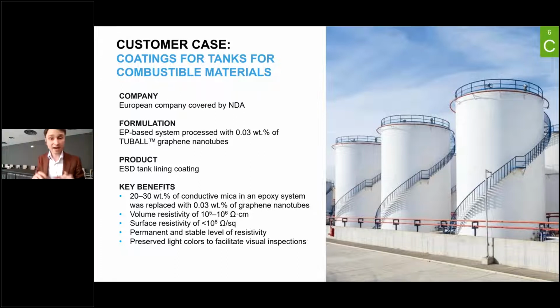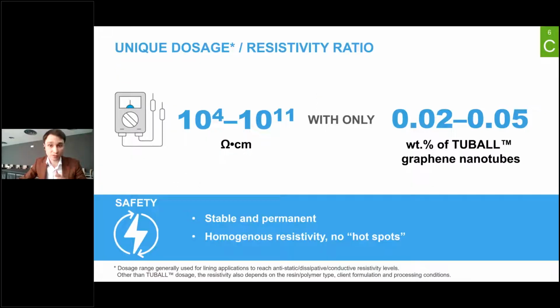And the second reason, after some time, it will be much easier to inspect defects at internal surface of tank lining coatings if it's light. Also, of course, the cleanliness of the tank will be much easier to inspect if tank lining coatings is light. But besides that, TUBALL allows to cover full range of requirements, which we see today on the market. For example, only 0.02 to 0.05 weight% of TUBALL carbon nanotubes will be able to cover 10^4, 10^11 ohm centimeter volume resistivity and surface resistivity.